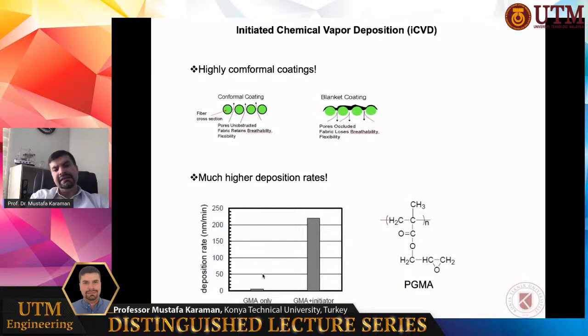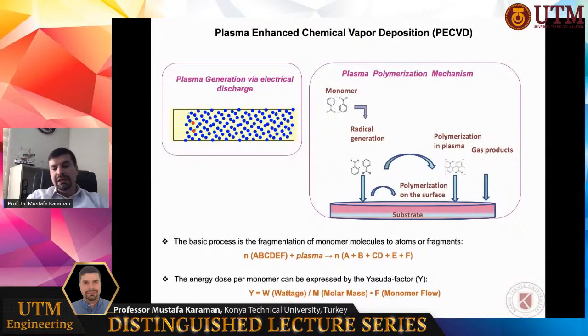And here you can see the improvement in the deposition rate. Without initiator molecules, deposition rates are very, very low. But in the presence of initiator, here you can see the improvement in the deposition rate. Okay, this was the story behind ICVD.